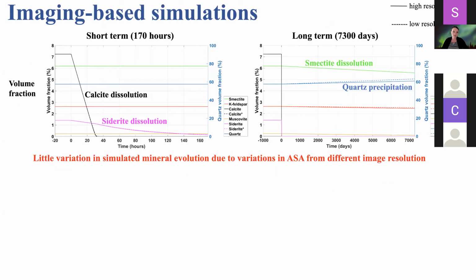Let's look at the results now for the imaging-based simulations. So this is the evolution of mineral volume fractions. We have the short time scale on the left and the longer time scale on the right. At a time of 0 is when the CO2 saturated brine enters the mineral cell. So this is the background conditions. And then the simulation results using surface area from the high resolution images are the solid lines, and the lower resolution images are the dotted lines.